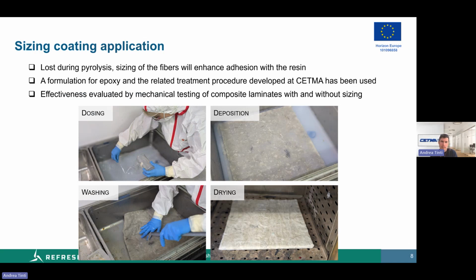Well, then the possible application of a sizing coating on the recycled mat has been studied. The sizing of the glass fibers, of course, has been lost during the thermal treatment, and it could be useful in enhancing adhesion with the resin in the new composites. We used a formulation for epoxy and the related treatment procedure at laboratory scale, and the effectiveness of this treatment was evaluated by mechanical testing of composite laminates manufactured with and without the sizing applied.